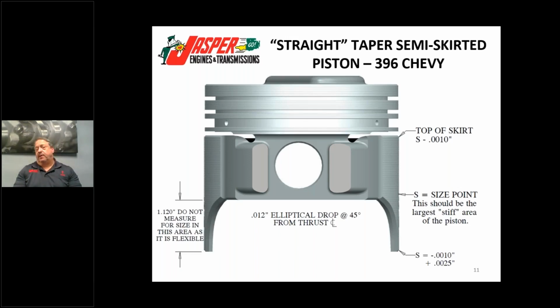What we make sure of, if I've got a nice combustion bowl and/or any release areas, is that we don't make those sharp. One of the worst things you can do in a diesel that has a nice diesel bowl is come out with a sharp edge, because as injectors go, over time you'll have fracturing from thermal cycling. So we do things for some performance engines, like for a customer with an 800 horse Duramax. We go ahead and what we call de-lip those areas and make sure that bowl is nice and smooth to try to prevent some of that. Normally, the most that you can probably ever cut off a diesel piston without having a problem is going to be 10 thousandths, most generally 5.